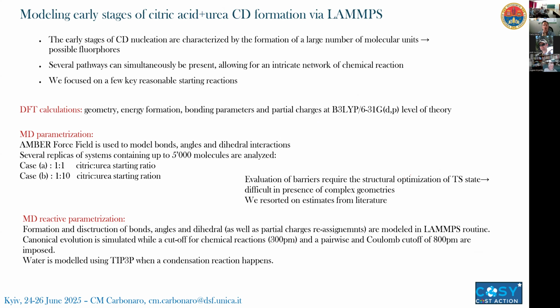So the approach was to model the early stage of the formation of carbon dots made by citric acid and urea. This was done by using DFT calculations and molecular dynamics parametrization in order to have a clear idea of how each molecule which is formed during the synthesis can interact with each other in order to give either the molecules or the carbon structure.